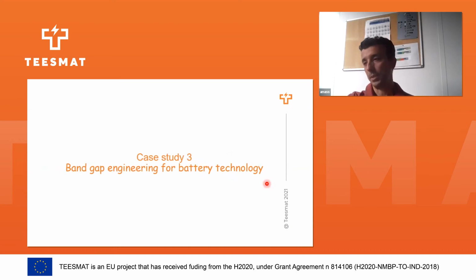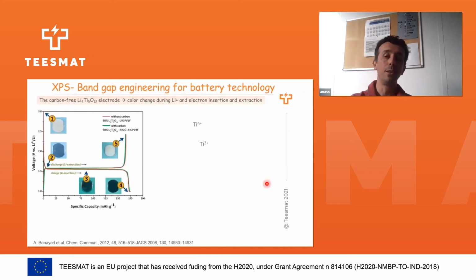Here I will go to the third case study, which is band gap engineering for battery technology. I will give the example of LTO, lithium titanium oxide, Li4Ti5O12. As we know from the literature, LTO is a material with SEI-less growth because it works at 1.5 volts above lithium voltage. This material is characterized by a plateau, which corresponds to a biphasic structure where we can insert 3 lithium, and move from phase Li4Ti5O12 to Li7Ti5O12.